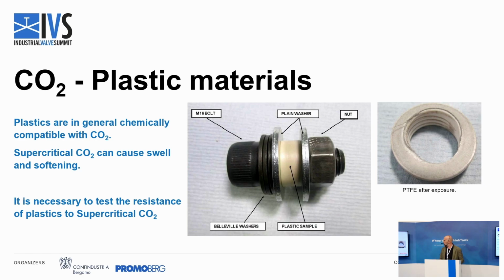We stressed the plastic rings with 5% of deformation. Is it correct? 5%. 5%. We put this plastic ring with this compression in a supercritical CO2 environment, and we actually discovered that PTFE, which is one of the most chemically stable plastics known to man, actually suffers from supercritical CO2, even if liquid CO2 or gaseous CO2 doesn't have this impact on the same plastic material. So again, the problem here is the supercritical state of carbon dioxide.